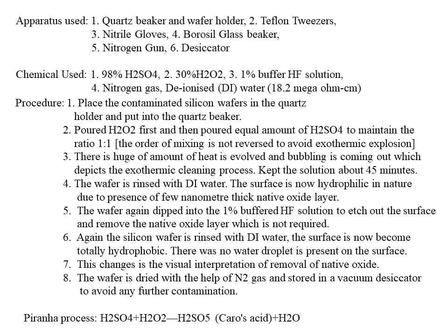After that we dry this wafer using nitrogen gas, because it is an inert gas; no other gases are used. Using a nitrogen gun, we flow it over the surface, and this wafer can be stored in the vacuum desiccator, in the glass system. The entire air can be sucked out using the vacuum pump, and we store it up to the next class.